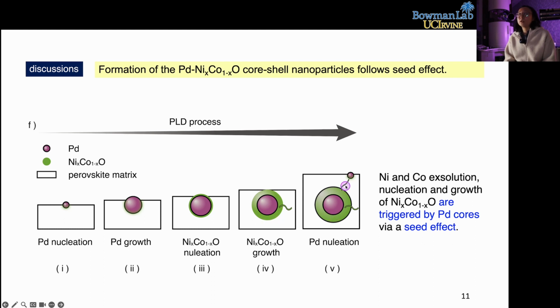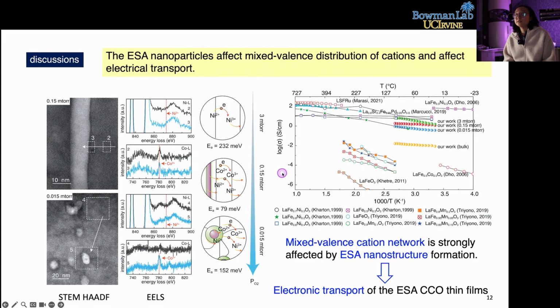And these nanoparticles are connected by percolating channels, which are enriched by nickel and cobalt. So this percolating channel will serve as a mass transfer pathway to form the shell part. We discuss how this nanostructure affects the electric properties of the thin films. We found the ESA nanostructures may affect the mixed valence distribution of cations and affect the electric transport properties.